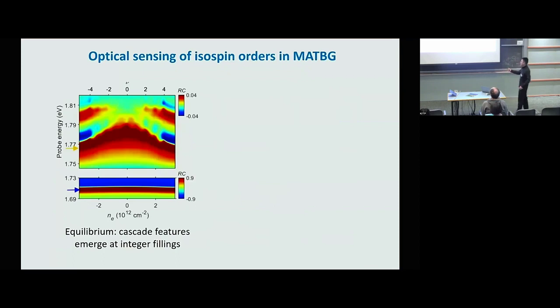But if you look at the 2s exciton, which is quite sensitive to the dielectric environment, then we can see some rich features, and these features reflect what's happening to electrons in the nearby graphene layers. Here, what we see is a series of cascade features at the integer fillings from -4 to +4. That's reminiscent of, or very similar to, the cascade features observed in other techniques. So again, this tells us that our exciton sensing or optical sensing technique is sensitive to the isospin orders, and we can use this to probe what's happening to the isospin degree of freedom.